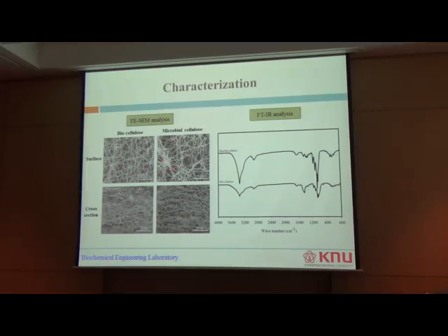As we can see, the SEM images show that the cellulose is composed of complex microfibrils, but in the case of the microbial system, the network is less compact as compared to the cell-free system. That is more compact, and the fibrils are tightly arranged. As well, if you see the cross section, the cellulose is produced in the form of a layered structure.